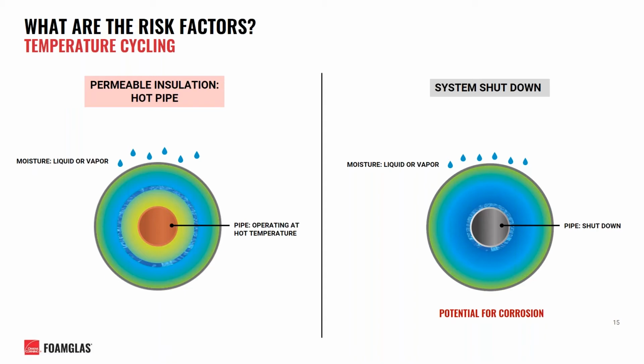Here, the liquid can become acidic or concentrated with chloride ions over time as it leaches from components of the insulation. Then, if the system is allowed to cool off during a system shutdown, this now chemically harsh solution can freely move to the surface of the pipe, where it settles and can cause rapid corrosion to take place.